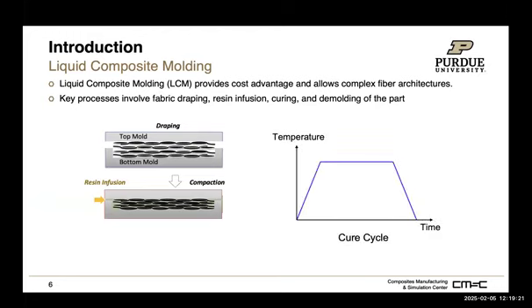And after that, you need what we call a curing process, because this usually is for the thermoset. So we apply a curing cycle. This is just like when you're dealing with epoxy for any of the repair projects you are working on. Some of the adhesives also require a temperature cycle for the curing. So we will need to apply the temperature, and once we allow the resin to be fully cured, then we reduce the temperature and do a demolding process. So from that, we expect to get a fully consolidated and cured composite part.